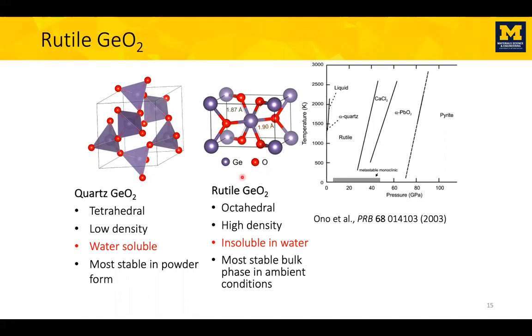On the other hand, the rutile is an octahedral material. It's the high density polytype, 50% higher in density. Most critically, it does not dissolve in water. So you can do all these usual etch techniques we use in semiconductors. And it's the most stable bulk material.